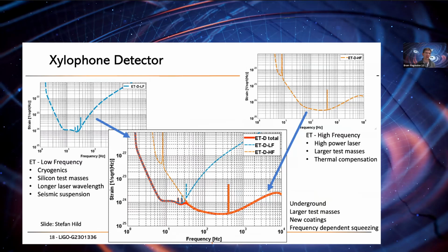So we have a low frequency detector, which only uses, on the top right, a sensitivity that is just looking at the low frequency and doesn't care about the high frequency. And with that, it operates at cryogenic temperatures to improve the thermal noise behavior, and uses silicon test masses, we'll get to that later on. We use a different wavelength and a suspension system which is much more advanced, much taller.